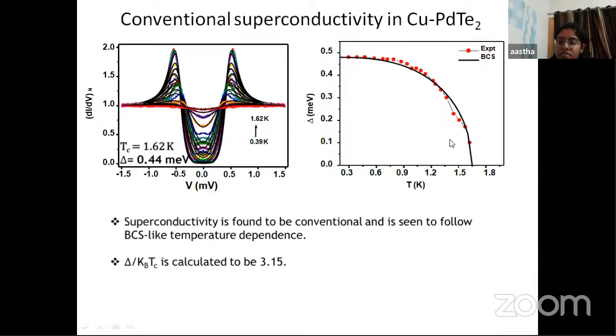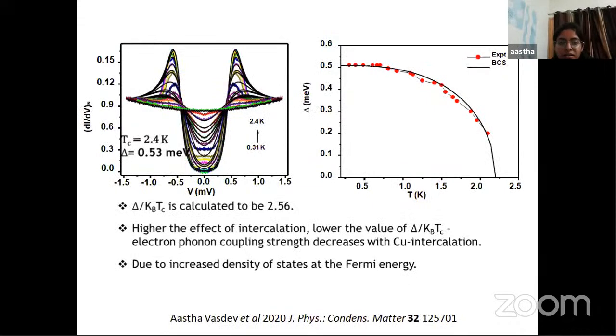If we look at the delta versus T dependence, the superconducting energy gap is seen to follow the BCS-like temperature dependence. If we calculate delta by kBTc for the smaller gap, where the effect of intercalation is lower, delta by kBTc is calculated to be 3.15. However, in the other regions where the superconducting energy gap was higher, the critical temperature is seen to be enhanced, while in the previous case it was the same as that of PdTe2. In this case the critical temperature is enhanced to 2.4 Kelvin, but the delta also follows the BCS-like temperature dependence. Now the calculation of delta by kBTc in this case is...